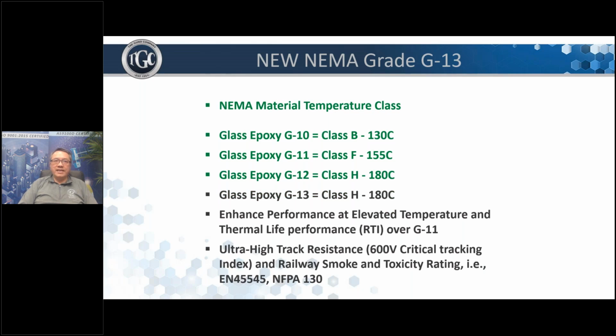And then there's another one called G13. If you look at it, G13 is Class H also. But what makes G13 special over G12? In case you need very high track resistance, in our industry there's a test called the CTI test. It's very hard to get to 600 volt. G13 material meets the 600 volt CTI, and it is also used in Europe for railway applications because of the smoke and toxicity grade. We have tested the G13 material and found out that not only does it meet the European EN 45545, it also meets the North American NFPA, National Fire Protection Association, 130.